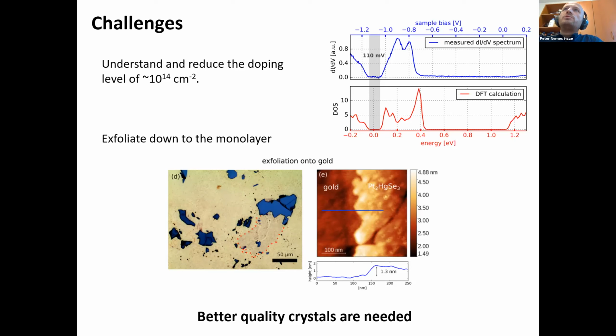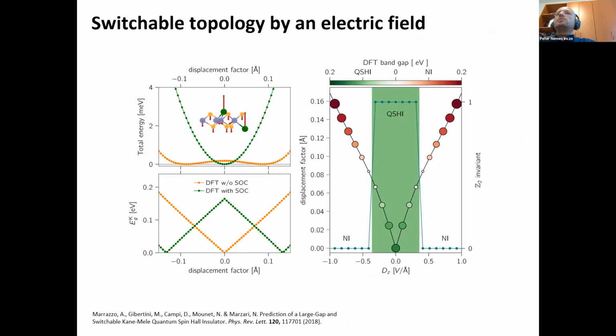Now, from challenges to opportunities, the story of this material is by far not over. So it has been shown in the first paper by Nicola Marzari's group that due to the fact that the 2 sublattices are located on either side of the monolayer, this material is susceptible to changes in the band structure when you apply an electric field that is perpendicular to the layer. And they have shown theoretically that you can switch the material into a trivial state if the out-of-plane electric field is large enough.